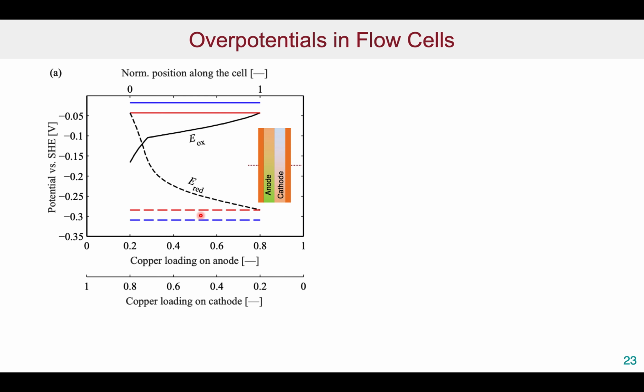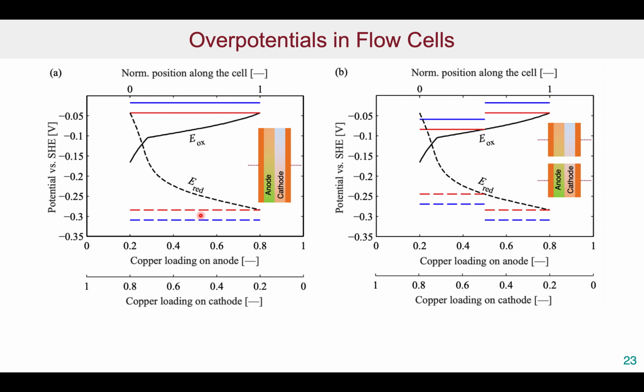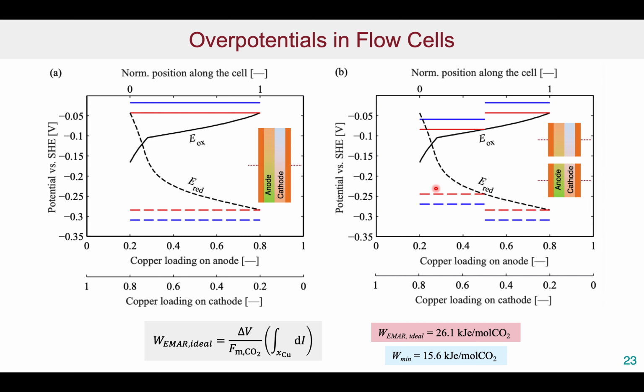We can minimize or reduce this energetic cost by using segmented cells, as shown in this case here, in which only part of the electrodes is at this potential, and the other section of electrodes is at this potential. So we can now reduce the energetic penalties somewhat by using segmented electrodes rather than one single electrode. And indeed, we'll find that here the actual ideal for this particular case would be 26 kilojoules rather than 15 kilojoules for the minimum case.